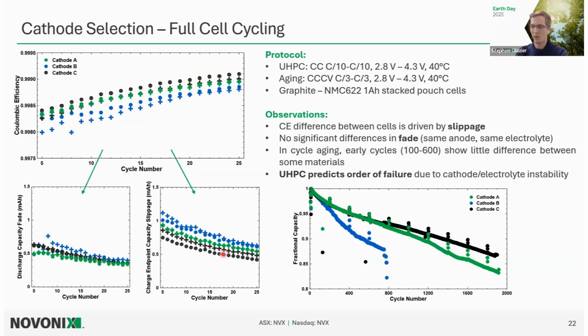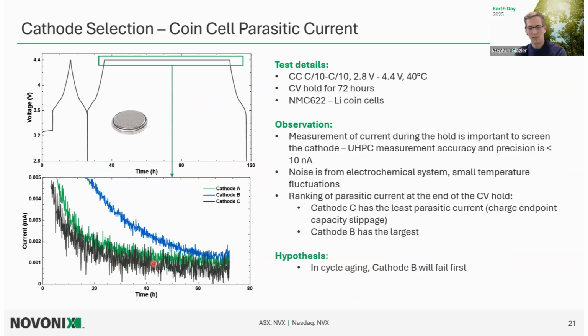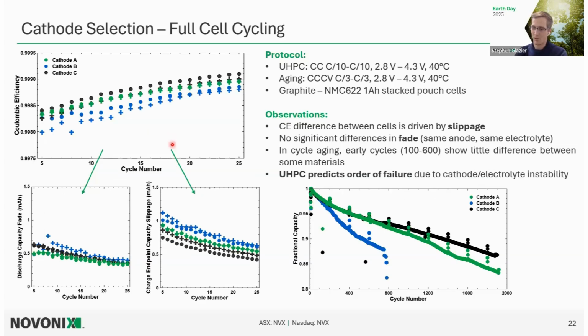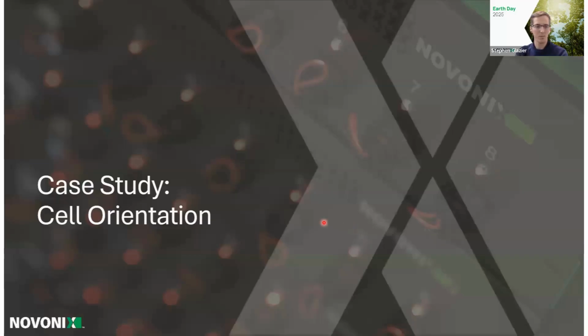So when we translate that later on, weeks later, we make full cells in the pilot line. Months later, we're testing the cells. We can see that that very early data measuring that parasitic current, which translates into our slippage-based mechanism, we can see that happen weeks later when we finally build out the cells and put them on UHPC testing. We can see the slippage in cathode B is the highest, and then months later, after testing the full cells in traditional cycling, those cathode B cells fail first, followed by A, followed by C, which is exactly what we saw just within days of making that material and sticking them in coin cells in the lab. So it's a really powerful technique to not have to wait for all of this information, which could be very valuable in terms of speeding up qualification of materials.